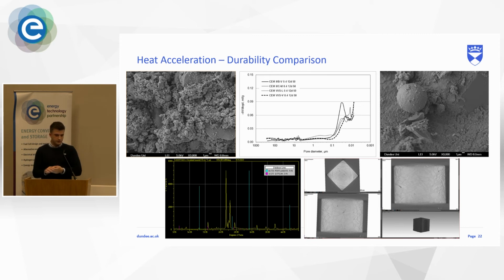It's probably important to mention at this stage that the underlying microstructure and the chemistry of concrete are immensely difficult to investigate, due to the multi-composite nature of concrete. The idea is that there's no single test that will show us what the microstructure is like within concrete. So what we're trying to do is as many microstructural tests as we possibly can, to show us the microstructure of such material from different angles.